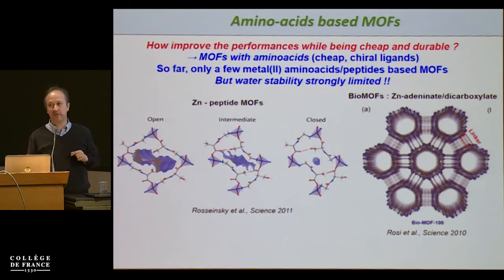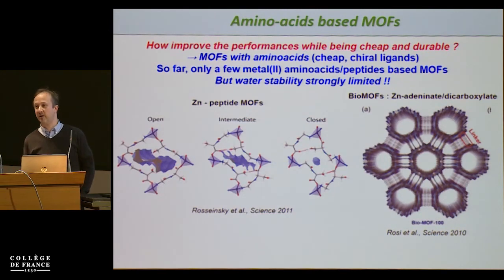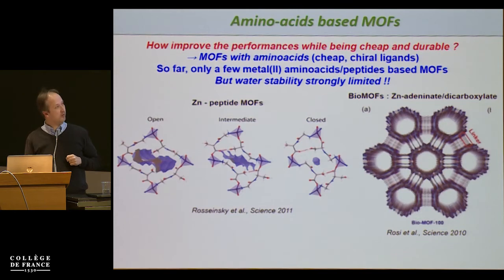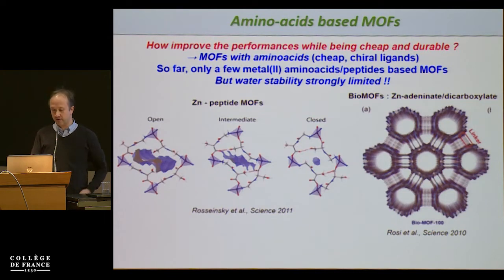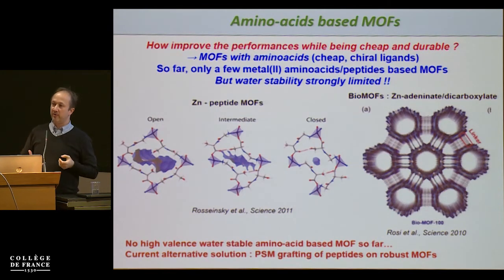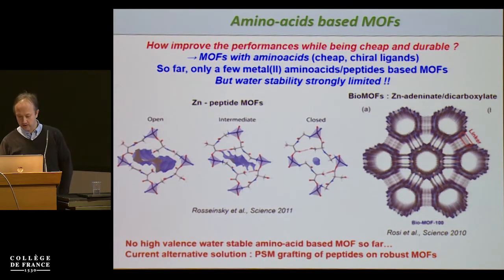Prior examples include work from Rosseinsky's group in Liverpool using a dipeptide with zinc, producing flexible structures that are totally non-water-stable. Another case from Natalia Rosi in the US used a combination of adenine and a dicarboxylic acid — not a pure amino acid MOF — forming a very nice mesoporous structure, but again with insufficient water stability for proton conductivity applications. There was also an alternative approach using post-synthetic grafting of amino acids inside porous MOFs, such as the work of Jerome Canivet and David Farrusseng in France.